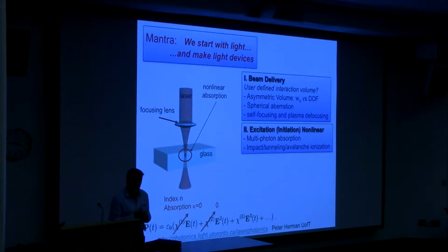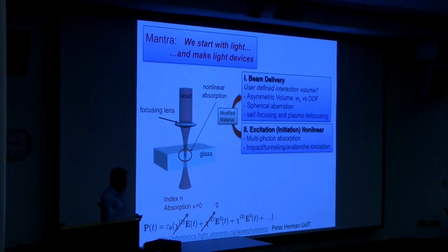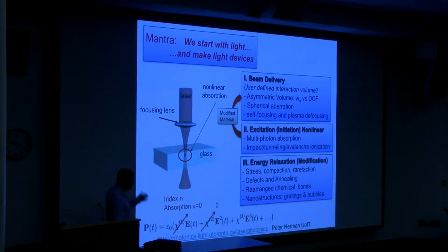There are dozens of pathways that this can turn on that seem complex and maybe discouraging. So you can drive, for example, a multiphoton absorption, but then an electron is generated, a free carrier is generated. Those in turn can allow avalanche ionization. And then further, you're modifying the material, so the latter part of the pulse sees this modification and takes a different path than the first part of the laser will follow. And so this modification plus these effects cycle around several times, so it just seems like a dog's dinner that you really cannot get a reproducible or good outcome, you might think. It seems impossible to control this wild, ultrafast interaction.